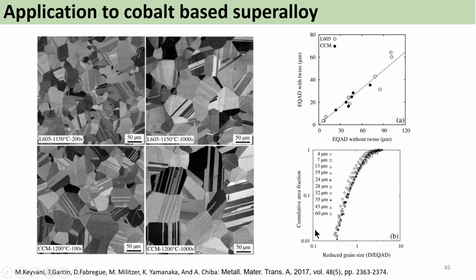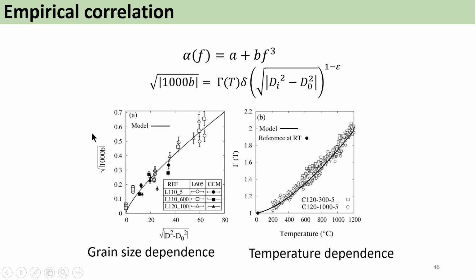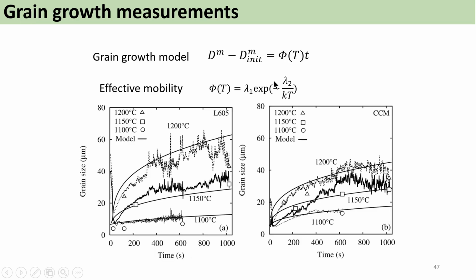We have developed this calibration using these B parameters, the same as we have seen in austenite and nickel-based superalloy. You see here there is a good correlation between these tests. And in addition to the case of nickel-based superalloy, what we have done here is complete this calibration with a temperature contribution, so as to be able to account for changes in temperature during the heat treatment. You see here this contribution in temperature varies slightly non-linearly in the temperature range that we have measured. And so by simply using this relationship, we are now able to extract the grain size in a sample during a heat treatment.